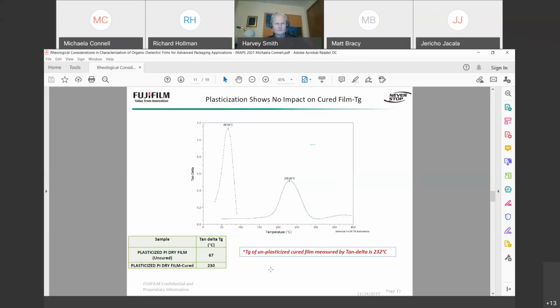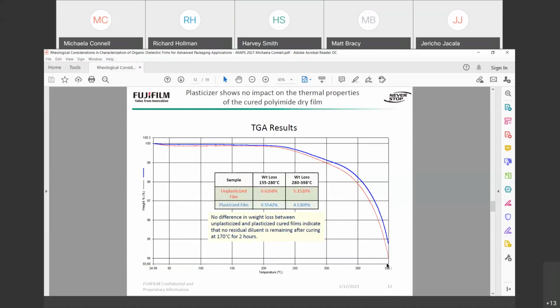In this figure, you can see the difference in the thermal properties between the cured and uncured plasticized films. When we look at the Tg of the cured plasticized film, the Tg is 230 degrees Celsius, which is almost identical to the Tg of the unplasticized film, which was measured at 232 degrees Celsius. And then when we're looking at the TGA results, there is no difference in the weight loss between the unplasticized and plasticized cured films, indicating that no residual diluent is remaining after curing at 170 degrees Celsius for 2 hours. This result shows that there is no impact of plasticizer on the thermal properties of the cured polyimide.